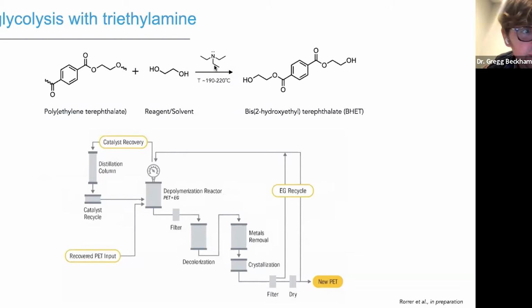This is triethylamine. Many of you know this is a common laboratory reagent. It doesn't smell very good, but it's quite a basic molecule, as you can see and probably know. It has quite a low boiling point, much lower than the reaction temperature of 190 to 220 degrees C. In the presence of ethylene glycol, one can do PET glycolysis to make bis(hydroxyethyl) terephthalate, BHET, which conveniently can precipitate from ethylene glycol as a solvent.